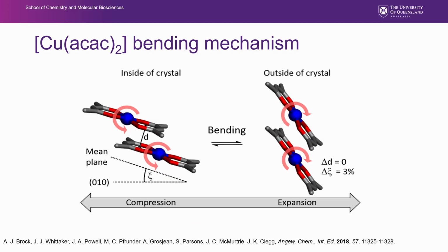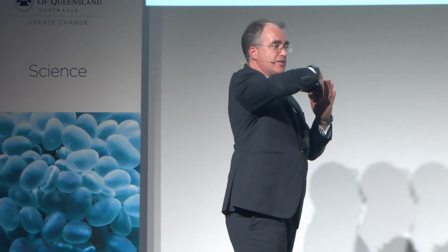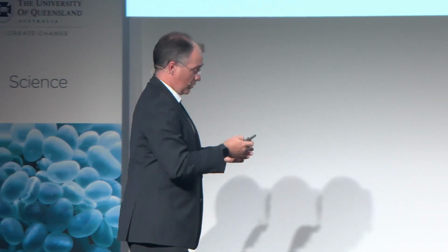Where on the inside of the crystal, where we're seeing compression, we see the molecules rotate to become more planar relative to the end of the crystal. And on the outside where they elongate, they rotate essentially in the opposite direction, getting longer. So just by rotating pairs of molecules, we can change the size and shape of the crystal. And whether that's us doing it or whether, I suppose it's the other way around, as we're bending the crystals, we're changing these molecules to change their orientation on the atomic scale.